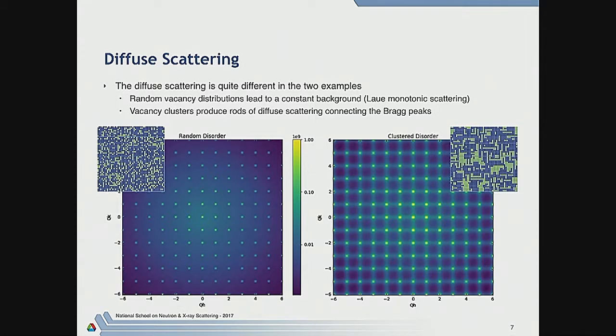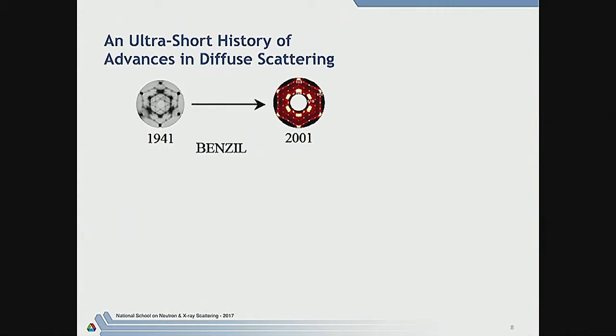So if you have completely random occupation, then throughout reciprocal space you just see what's called Laue monotonic scattering, which is very broad and actually centered at Q equals zero. But if you have cluster disorder, as in this model, then you see quite distinctive structures, such as these rods connecting the Bragg peaks. And so clearly, you can tell the difference in diffuse scattering between these two models. And this is the 1941 data in Benzil. It was measured all that time ago.